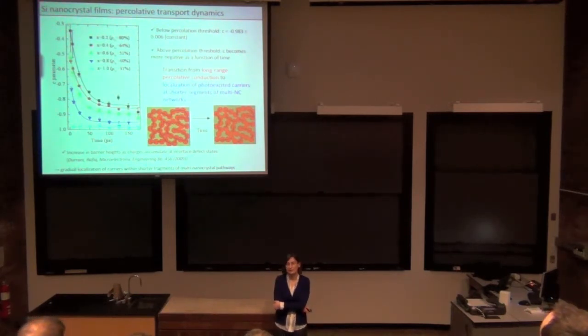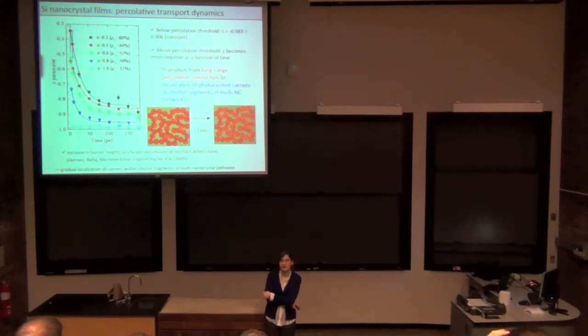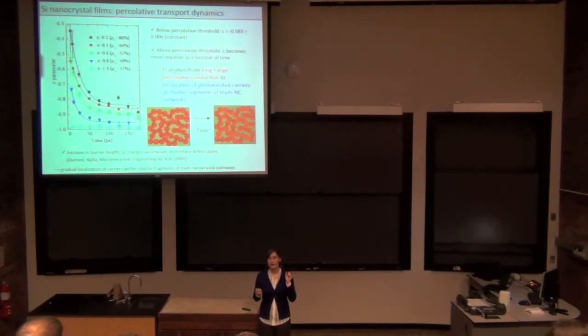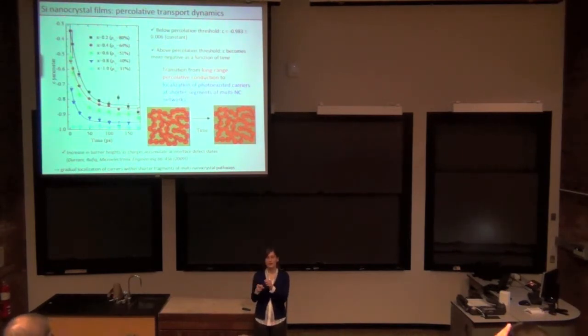When you first started talking about scattering and introduced this parameter, you mentioned that you have done some Monte Carlo studies. Can you elaborate on that a little bit more? Yes. We basically modeled the nanocrystals as an array of boxes. In this box, you introduce the carrier and then apply an impulse of electric field. What you're varying is the reflectivity of those boxes. For example, if it's 80%, then there's an 80% chance of it going back. The other 20% exits the box and enters from the other side. By varying this reflection coefficient and the size, we were able to get exactly this kind of behavior.